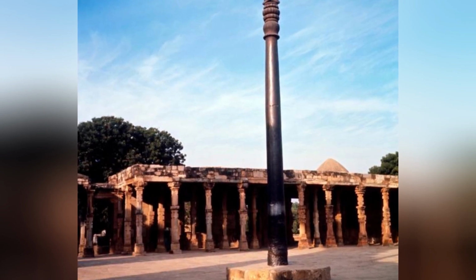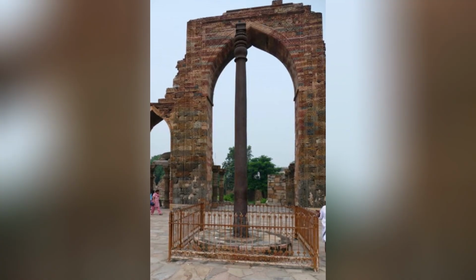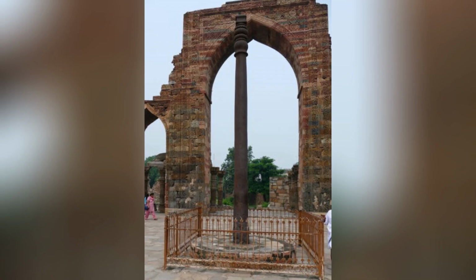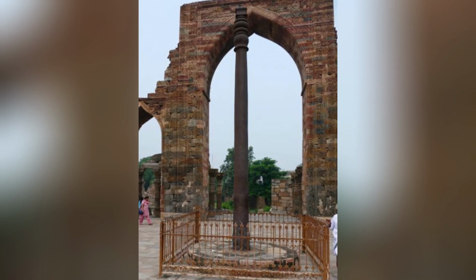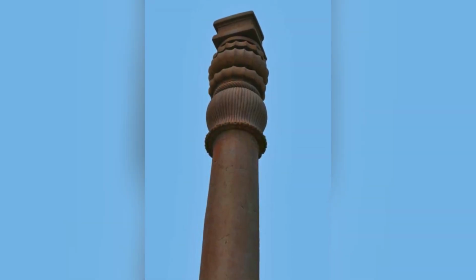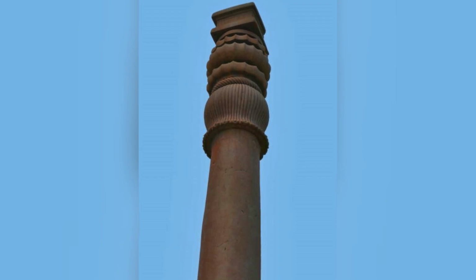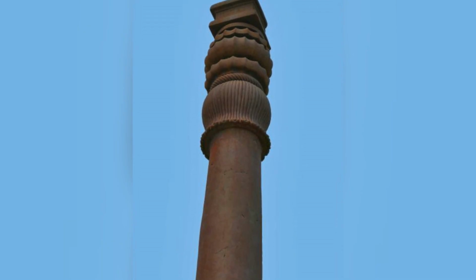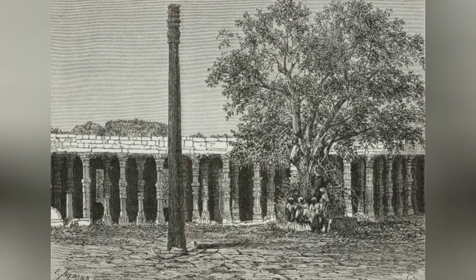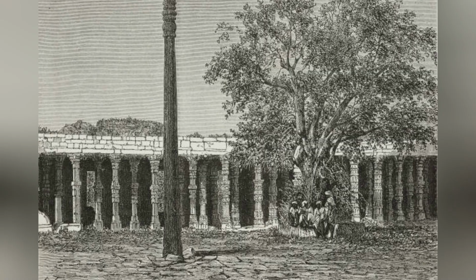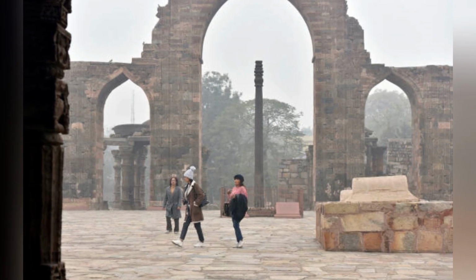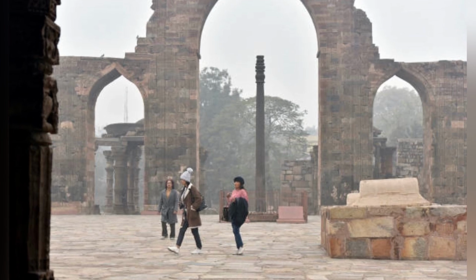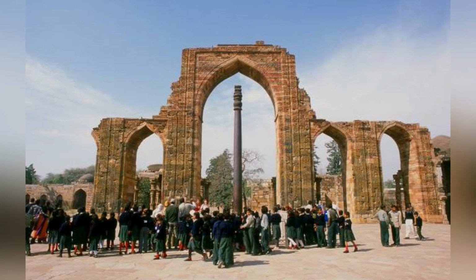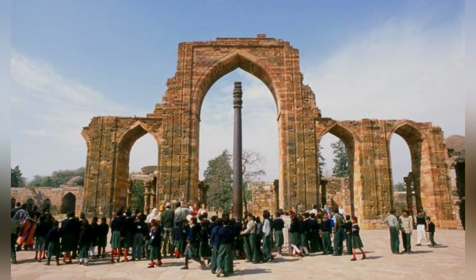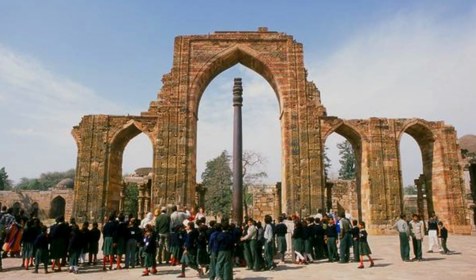The experimental validation of the misawite film's self-healing capability has been one of the most important confirmations of Balasubramanian's model. In controlled laboratory experiments, researchers have deliberately scratched or damaged the protective film on samples of phosphorus-rich iron and have then exposed the damaged samples to the cyclic wet-dry conditions that simulate the Delhi climate. The results have consistently shown that the damaged areas of the film are repaired within a few wet-dry cycles, with new misawite forming at the damaged sites and sealing the exposed iron from further corrosion. The speed and the completeness of the repair process are impressive, with the damaged areas showing full recovery of their protective properties within weeks of the damage being inflicted.